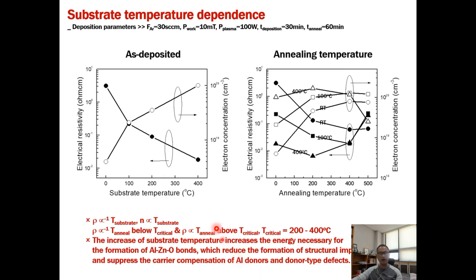Fourth, I will show substrate temperature dependence. In the left figure, electrical resistivity decreases with the substrate temperature. Electron concentration is vice versa. In the right figure, electrical resistivity decreases with annealing temperature until 300 or 400 degrees centigrade. Above it, electrical resistivity has a tendency to increase. Electron concentration is vice versa.